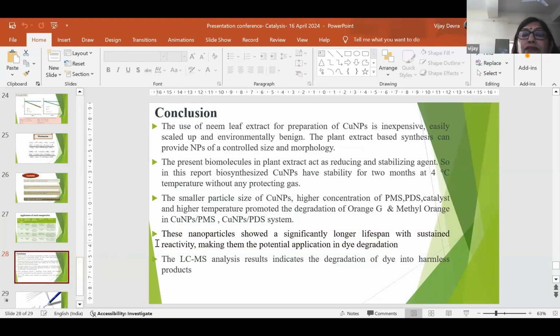And the smaller size of the nanoparticles and higher concentrations of peroxomonosulfate, peroxodisulfate, catalyst, and higher temperature promote the degradation of Orange G and Methyl Orange dye in both the peroxomonosulfate and peroxodisulfate systems. And the LCMS analysis results indicate the degradation of azo dye into harmless products.